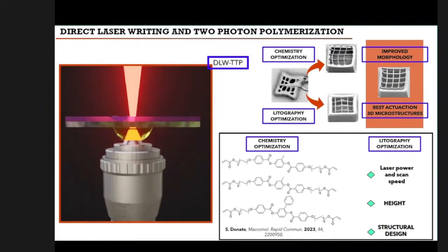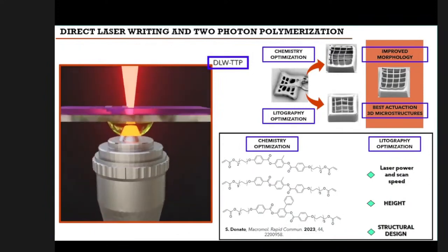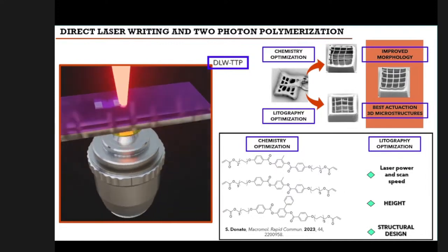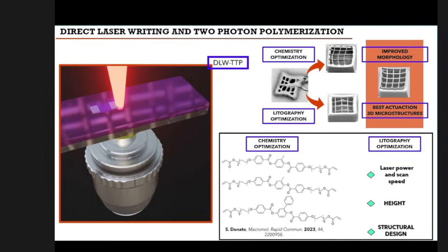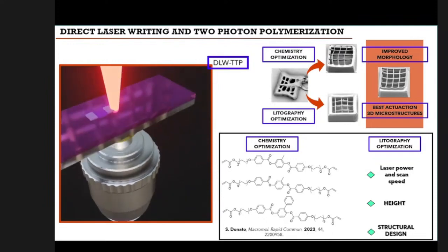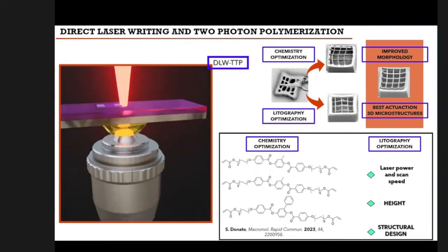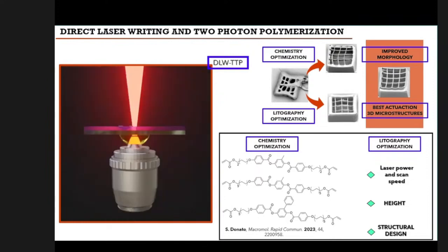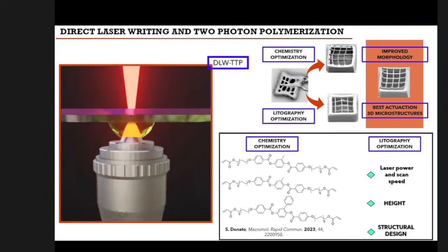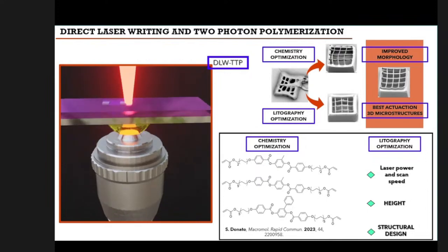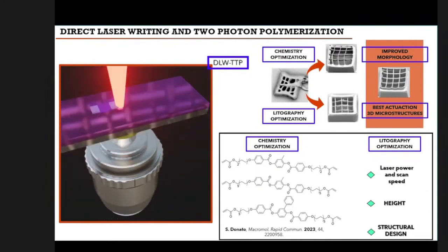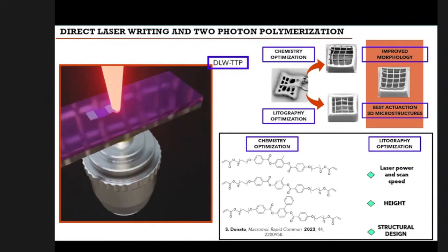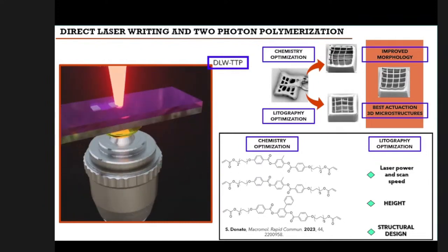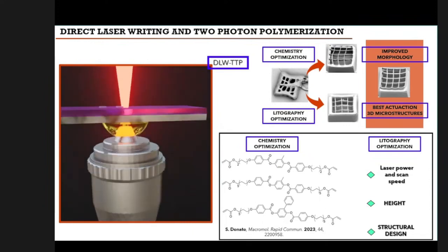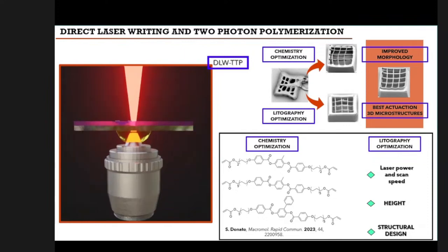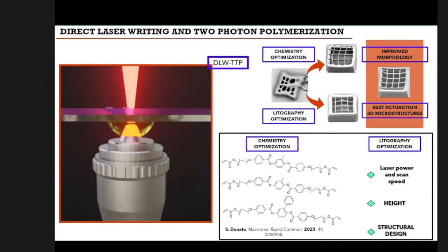So first, the realization of microstructures calls for a new kind of lithography technique, and I was able to use direct laser writing with two-photon polymerization, in which a near-infrared femtosecond laser is tightly focused into the liquid crystal cells, and allows me to obtain the photopolymerization in only one spot of the liquid crystal mixture to obtain the final design that I previously prepared. In this case, to obtain well-shaped microstructures, I need a chemistry and a lithography optimization to obtain an improved morphology and the best actuation properties of the three-dimensional microstructures.